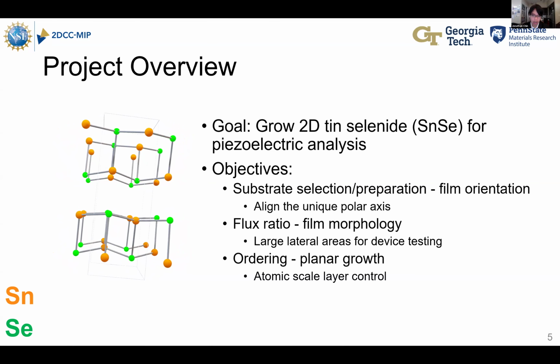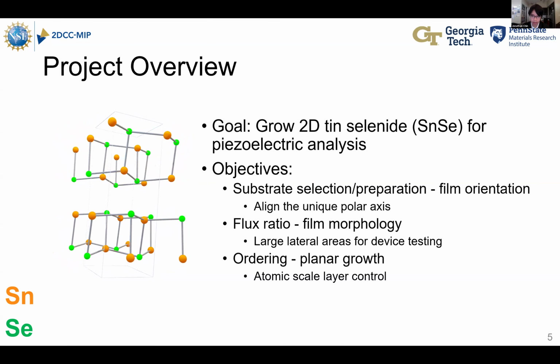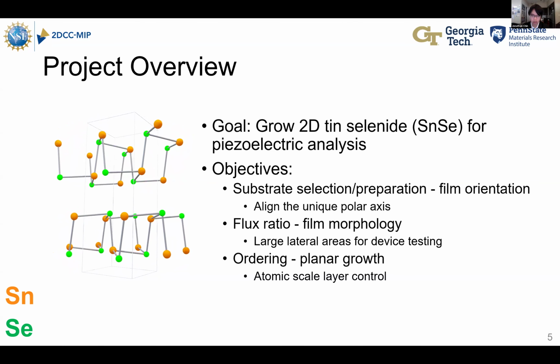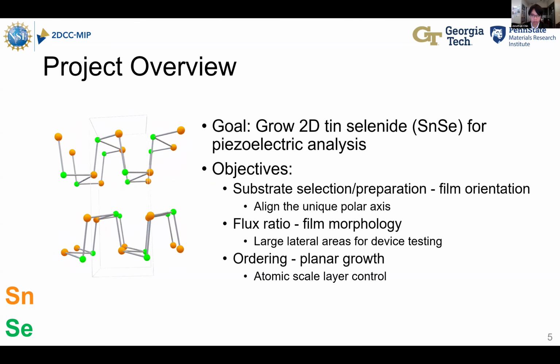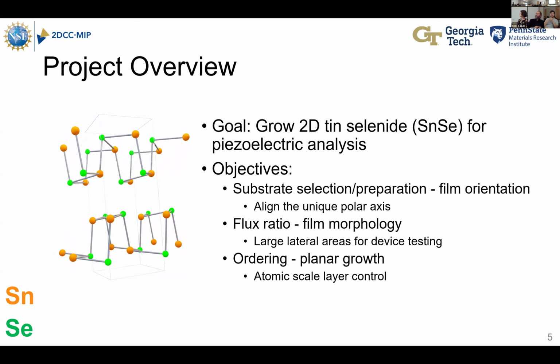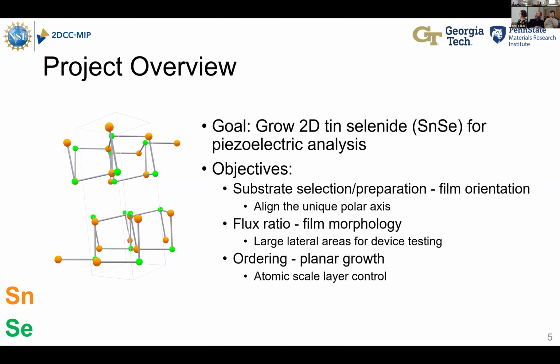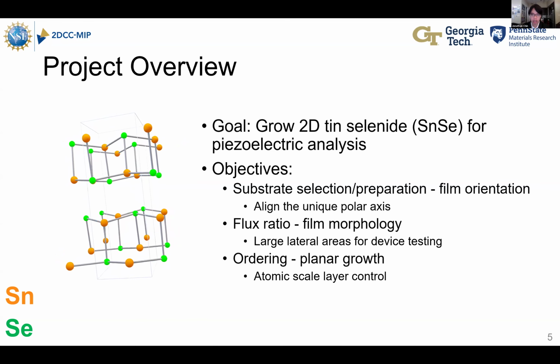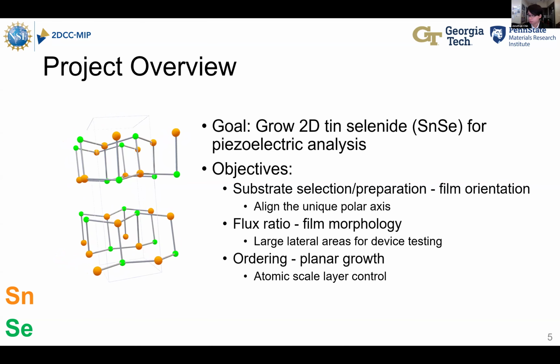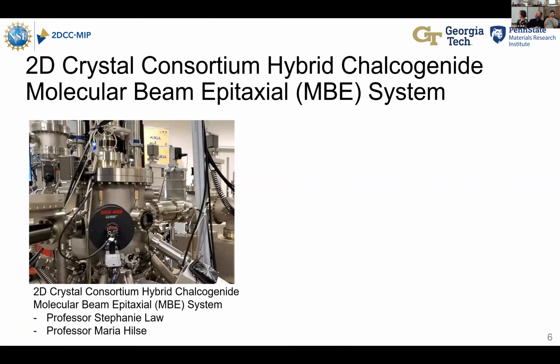So we need atomic scale layer control so we can get that monolayer and control the number of layers we have. We think we can do this by changing our selenium to tin flux ratio and the order in which we open our cells. Everything was done at the 2DCC chalcogenide molecular beam epitaxy system. I was hosted by Professors Stephanie Law and Maria Hilse, without whom this research would not be possible.